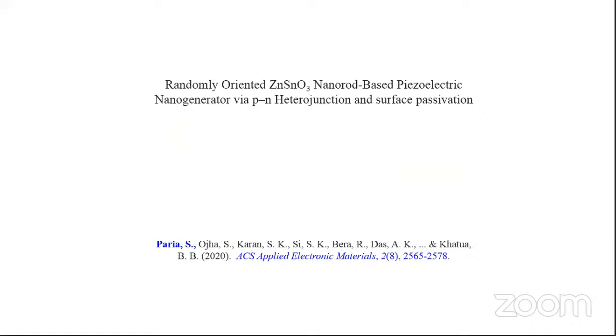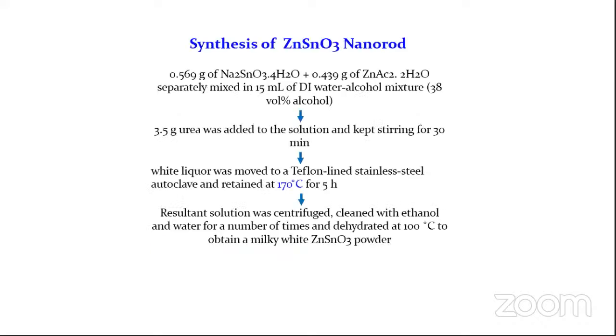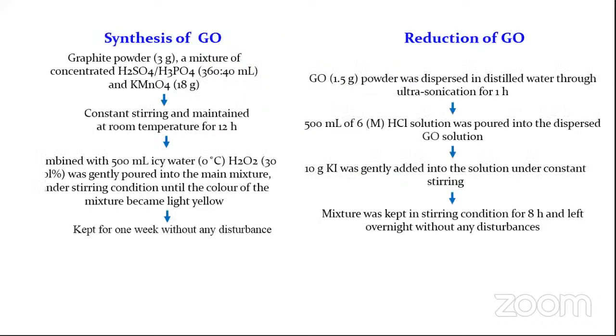Then in our second work, we have dealt with the different morphology of zinc stannate. We have optimized the output performance through a PN heterojunction and a surface passivation layer. For the synthesis of zinc stannate nanorods, we followed a simple hydrothermal method at 170 degrees centigrade for 5 hours. This is the synthesis of graphene oxide. The modified Hummers method was employed for the synthesis of graphene oxide, and for the reduction of graphene oxide, we have used KI and HCl medium.